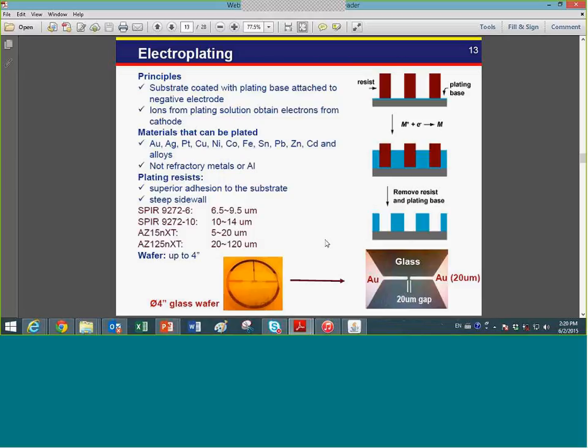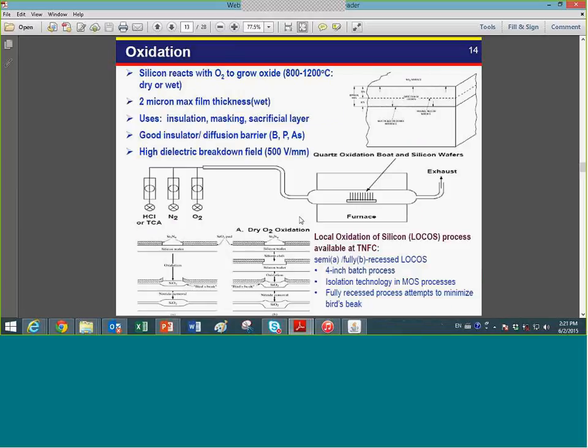And in addition to using liftoff for metal patterning, we can also do electroplating by patterning the resist on top of a seed layer, then electroplating and then removing the resist. Here's an example on a 4-inch glass wafer. We can pattern electroplated gold with a 20 micron gap and a 20 micron thickness of gold. Different materials, including nickel and copper, can also be plated.